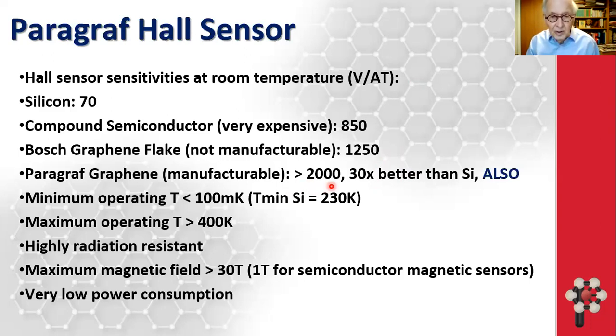It also works down to very low temperatures, less than 100 millikelvins, which is the lowest temperature we've tried, so less than that. A silicon Hall sensor's minimum temperature is 230 Kelvin. So that's a huge effect, meaning you can use a Hall sensor for cryo applications. We're now starting to sell our Hall sensors, and we've sold one or two to IBM, who are using them for quantum computing, because quantum computing is done at very low temperatures. So they're being used for quantum computing and other low temperature applications. Maximum temperature at the moment is 400 K, which we believe we can increase.